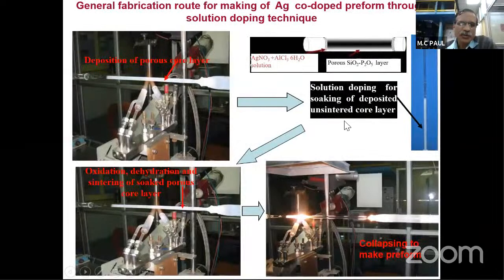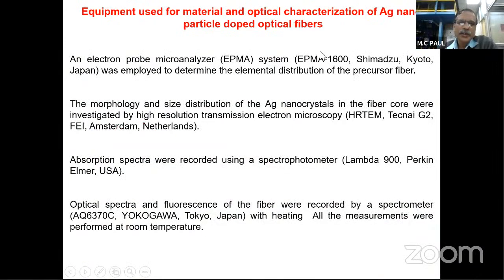Then soak this layer. After soaking, it goes to an oxidation and dehydration process, and then gives rise to sintering, collapsing, and finally we obtain the preform. This is the tool we have used: material optical characterization, EPMA, high resolution TEM, spectrophotometer, optical spectra, fluorescence spectra with heating, all of this.